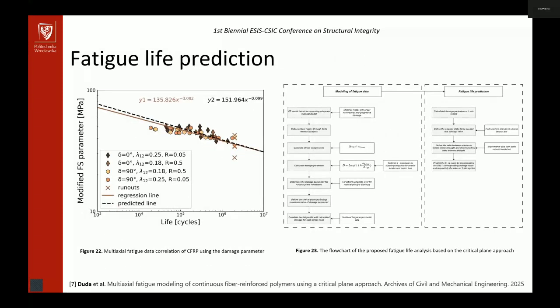For the fatigue life prediction, based on this, we decided to propose a quite simple method. We calculate the damage for 1 million cycles and associate it with the uniaxial load which can generate the same damage value, and then correlate this with the UTS value. However, this value needs to be for the tubular specimen, not for the flat one. We derive this curve, and the algorithm has been presented here.